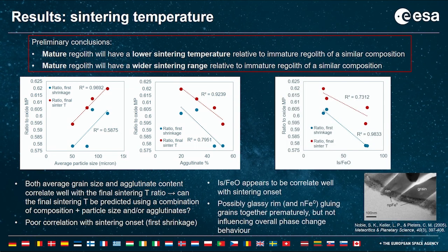And then if we look at the data against the IS/FeO, so that's the proportion of the iron that's in the nanophase iron state, and also the proportion of those glassy rims and the amount of the glassy rims on the particles, we see that this actually correlates better to the first sintering onset, but not as well to the final sintering temperature. And so our current hypothesis is that maybe the glassy rims on the surface of the particles is actually gluing the material together kind of prematurely, but it doesn't actually impact the overall phase change behavior. So it doesn't impact the final sintering temperature, but just does that initial gluing.